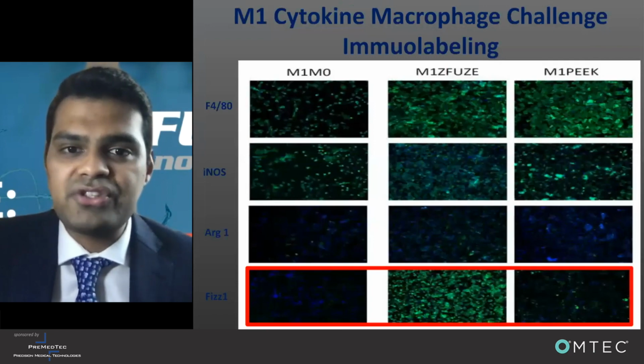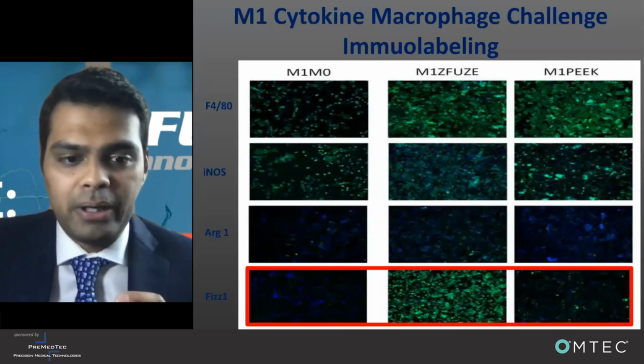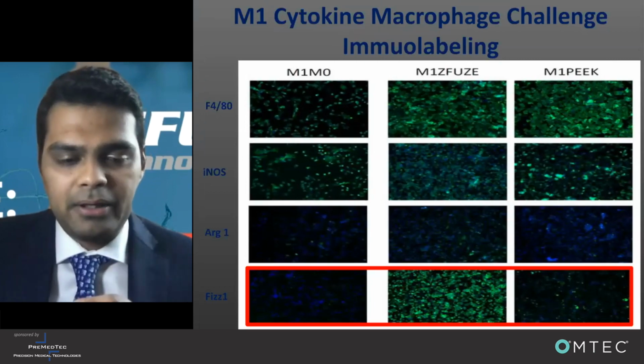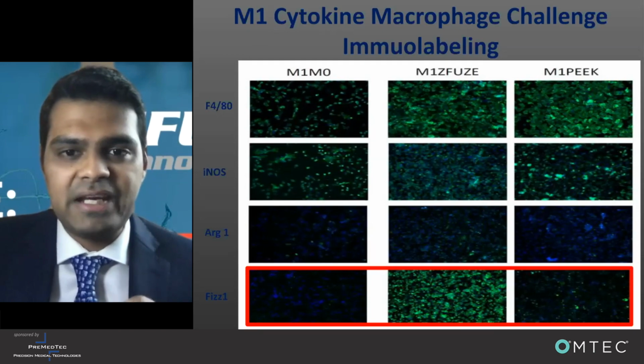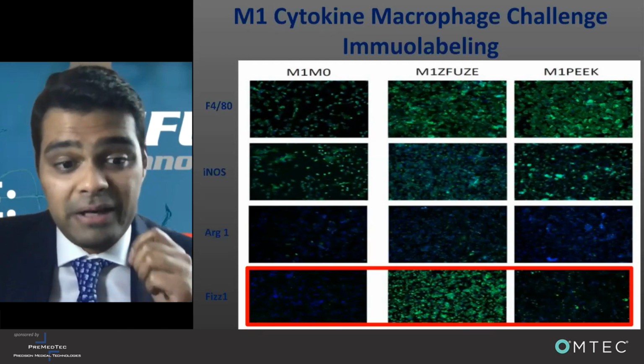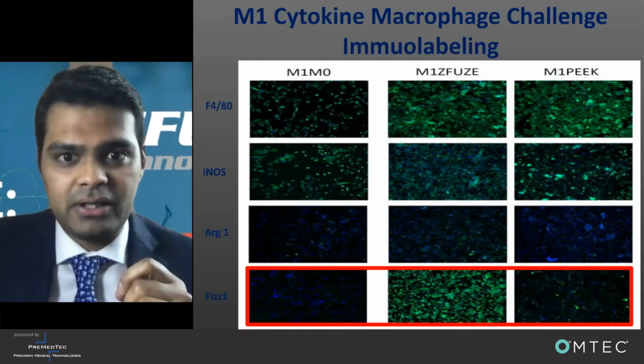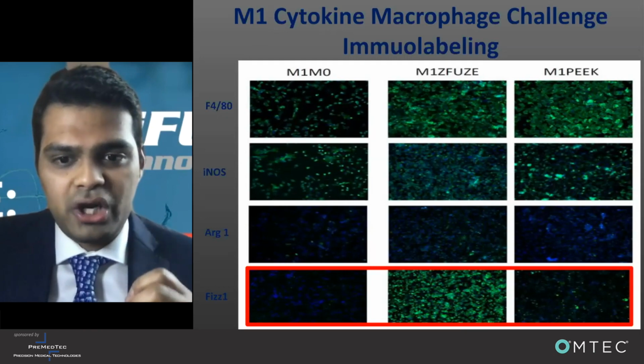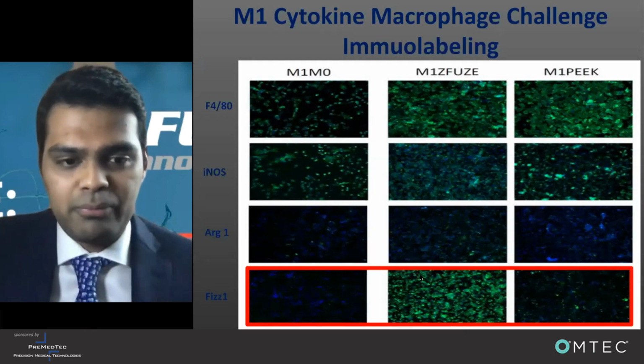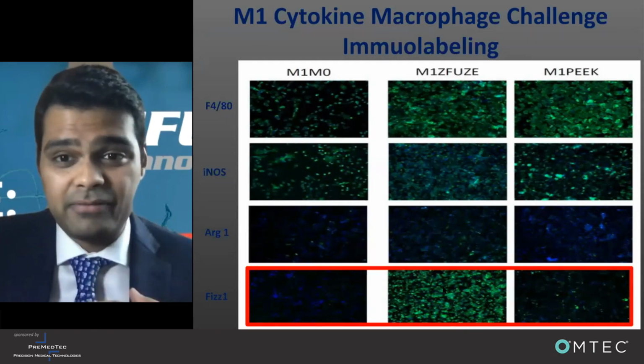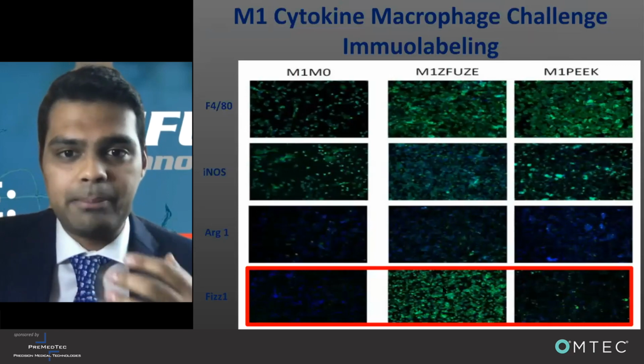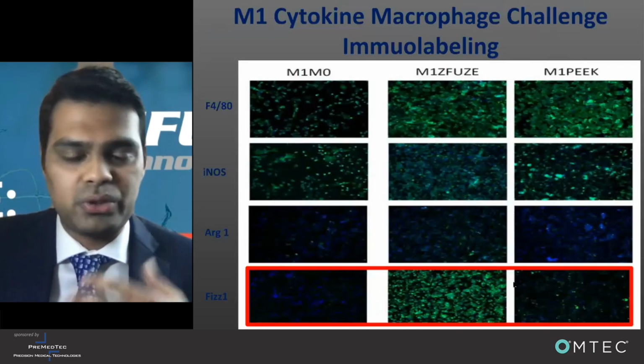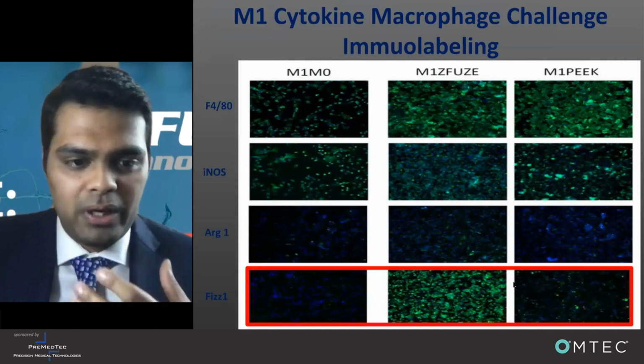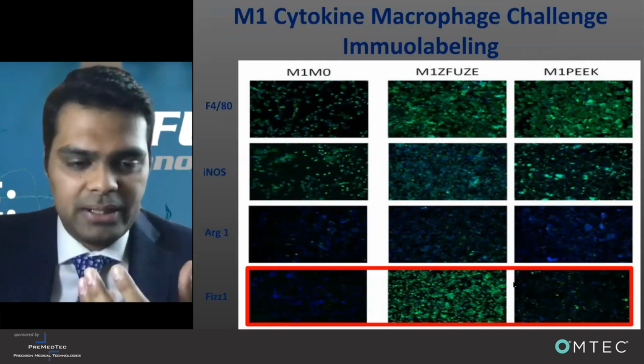Also, what was very interesting was when we gave it a pro-inflammatory push, we took these materials, brought about a pro-inflammatory insult, and what happened was, very interestingly, Z-Fuse, even after a pro-inflammatory insult, shuttled this pro-inflammatory state into an M2 pro-reparative state. And so that was very impressive on Z-Fuse versus, say, PEEK, which resulted in this M1 pro-inflammatory state actually staying put.